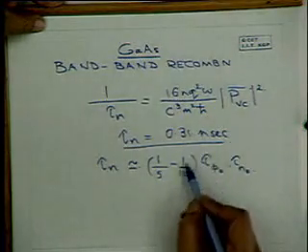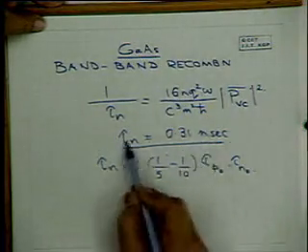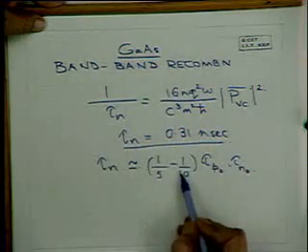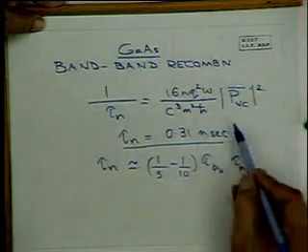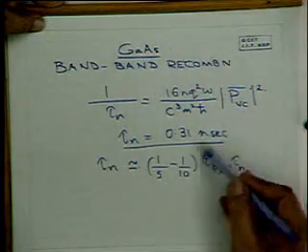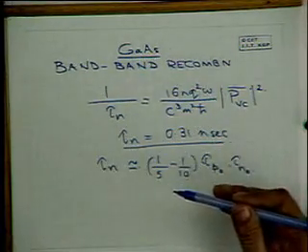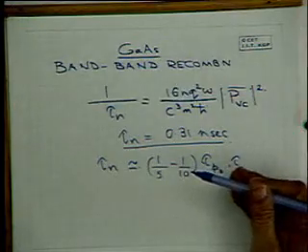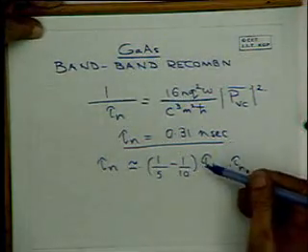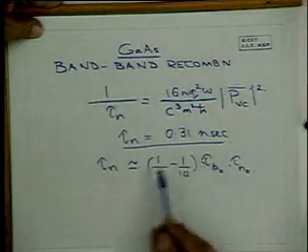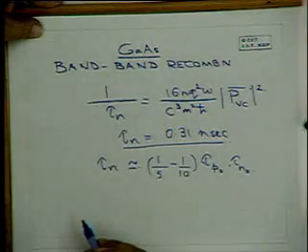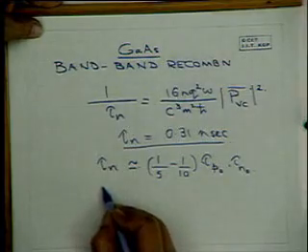So obviously, for these doping levels, band-to-band recombination is much more probable, is faster by a factor of 5 to 10 over recombination through impurities, donors and acceptors. And so this is a faster and more probable process.